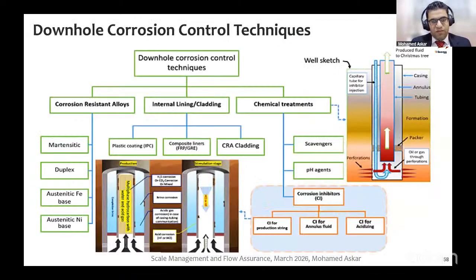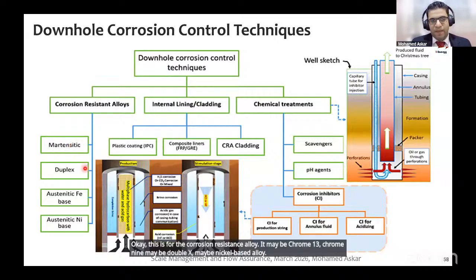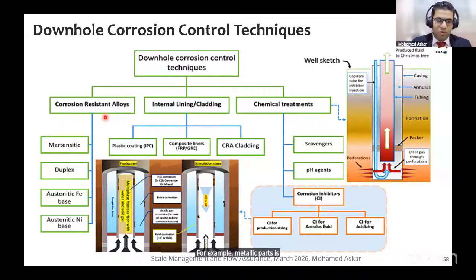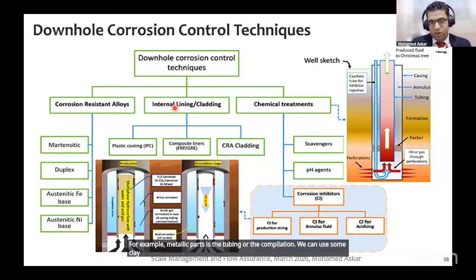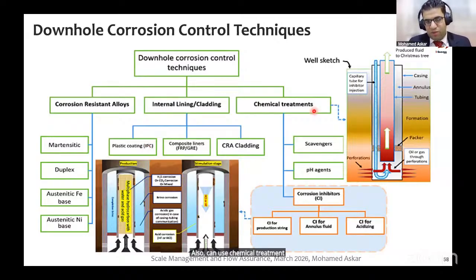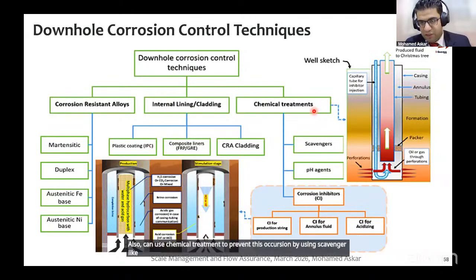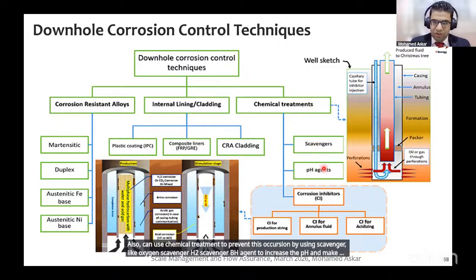Okay, this is for the corrosion resistant alloy. It may be chrome 13, chrome 9, duplex, or nickel-based alloy for the metallic parts, the tubing or the completion. Or you can use some cladding or internal coating to prevent the corrosion. This cladding may be corrosion resistant alloy or plastic parts or thermoplastic material. Also, you can use chemical treatment, such as oxygen scavenger, H2S scavenger, and pH agents to increase the pH and make the fluid basic, not acidic, because acidic promotes corrosion.